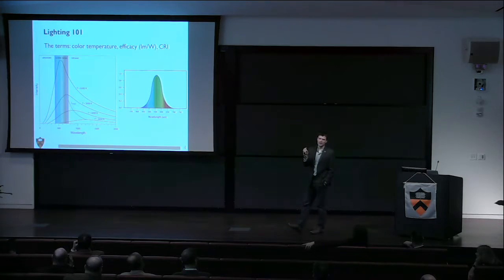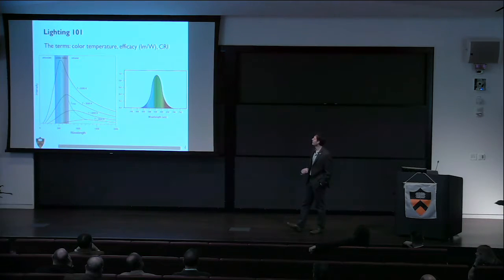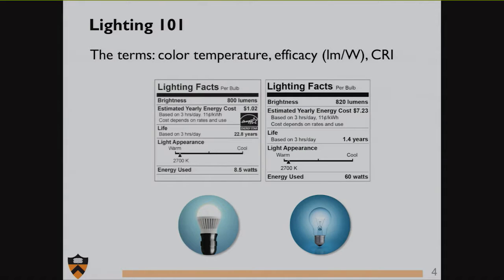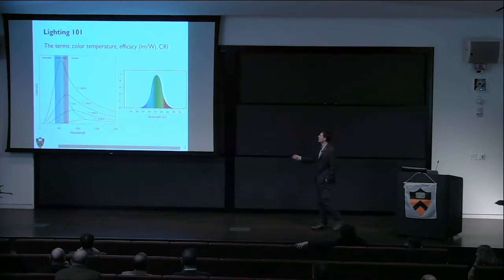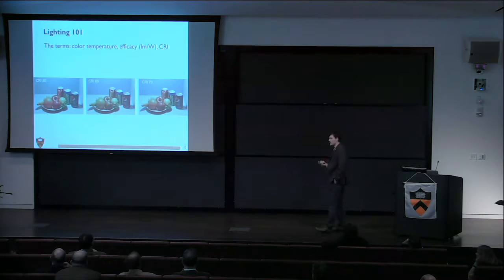When we look at the back of our light bulb, here's the 13 lumen per watt, 60 watt bulb with color temperature of 2700 K. The luminaire from solid state lighting has a much higher lumens per watt ratio, about 90 or so, and they also make the color temperature about 2700 K. Because it's been found you don't actually want 6000 K indoors. There's psychology that goes into optimal light sources indoors, and people like a warm white, not excessively in the blue part of the spectrum.